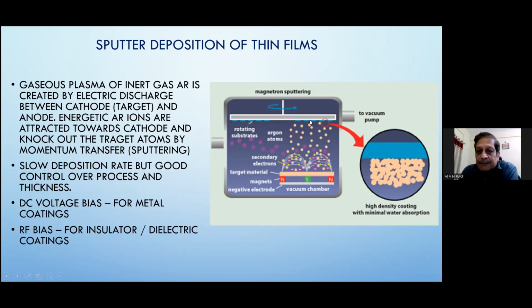And typically the distance between the sputtering target and substrate, in the case of sputtering systems, is maximum about 50 millimeters, 5 to 10 centimeters. That is the maximum gap, because the sputtering is happening very slowly, with a very low yield. We cannot keep the substrate too far away. Whereas in the case of electron beam gun and ion assist, there will be almost more than 30, 40 centimeters distance. Sometimes 50 centimeters also.